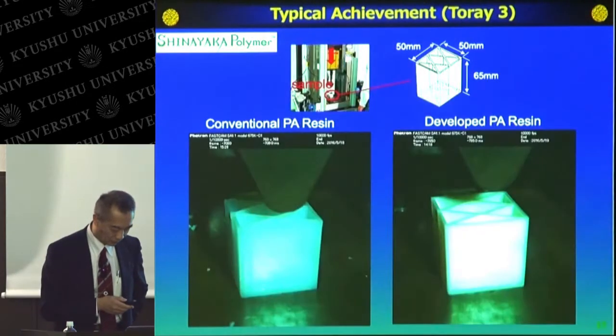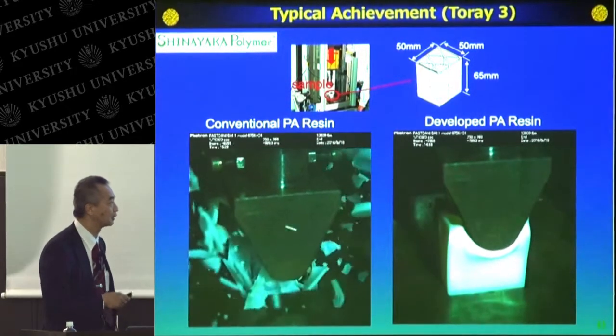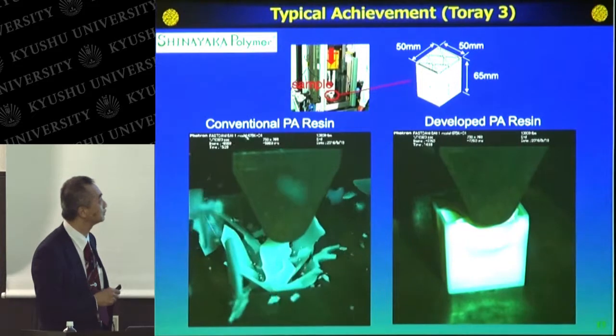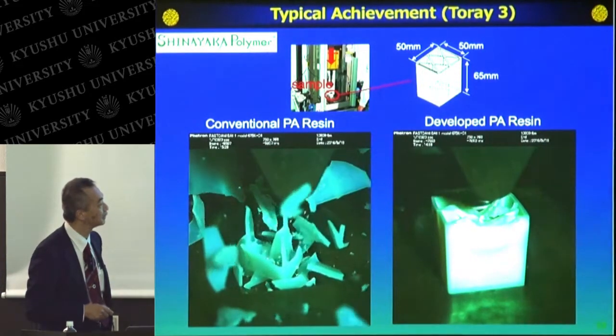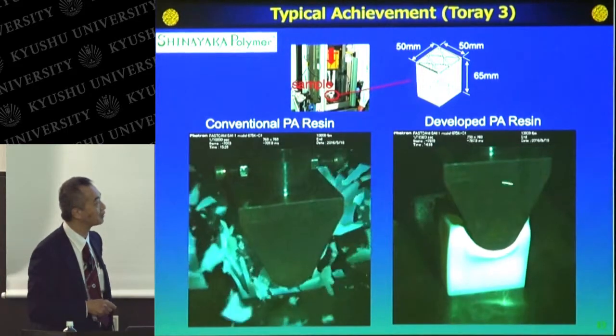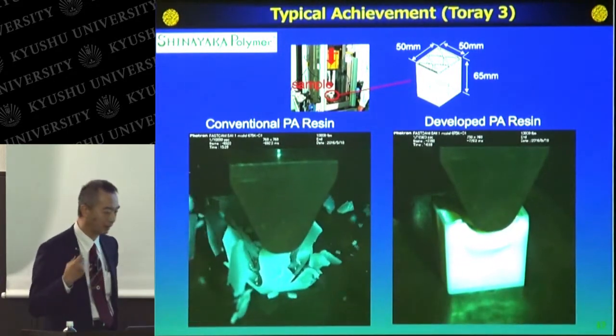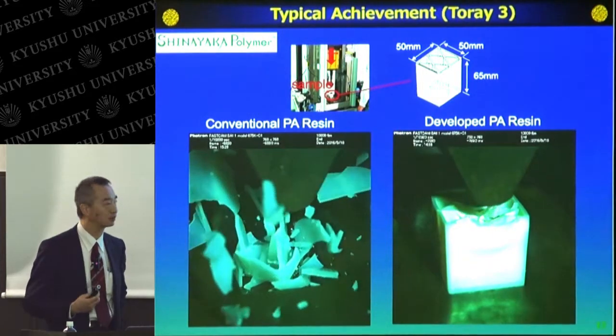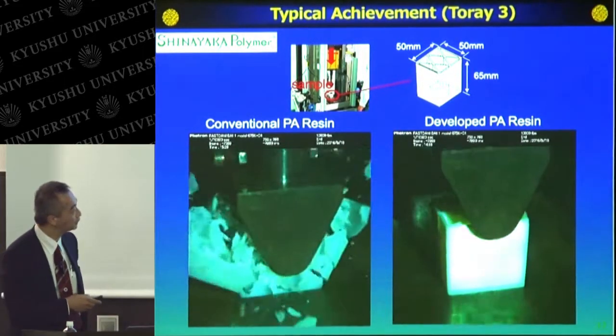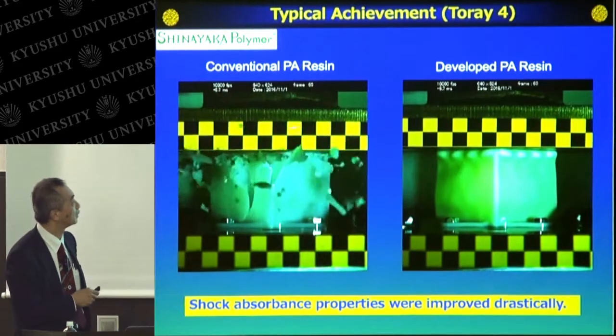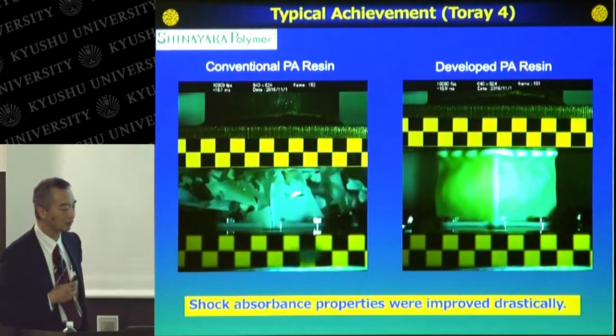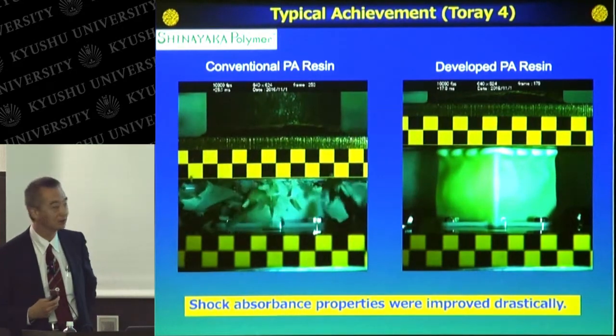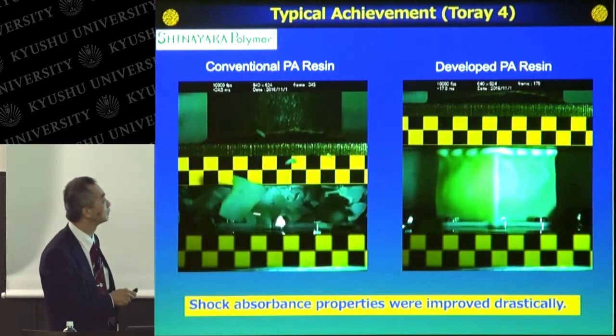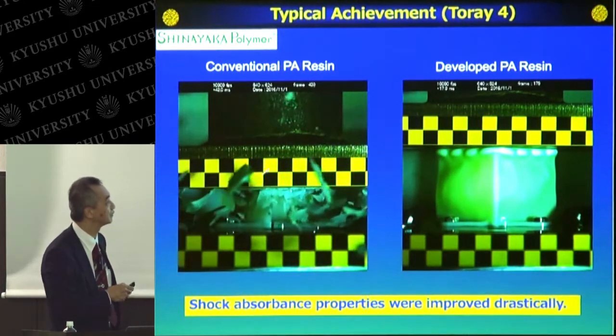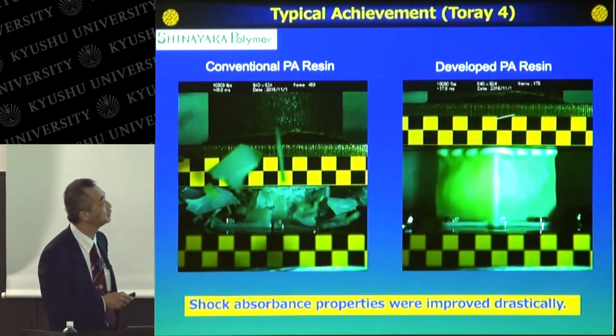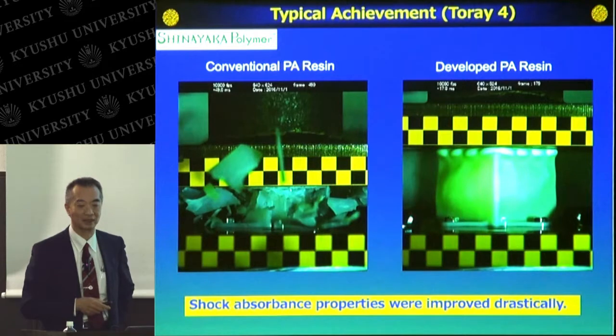Then the impact drop test results are completely different. So usually polyamide resin is brittle like this, but the developed polyamide resin does not collapse when they add only 5% of polyrotaxane. This technology is effective as a composite. These two polyamide resins have about 30% glass fibers. Then the conventional polyamide resin composite becomes more brittle. But you can see this newly developed polyamide resin does not collapse like this.